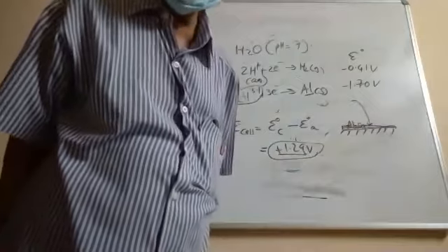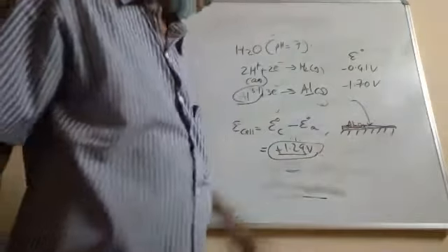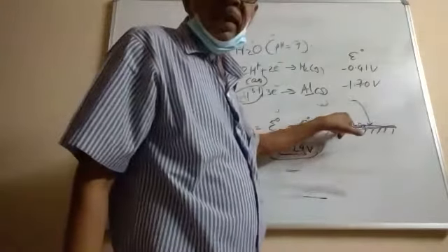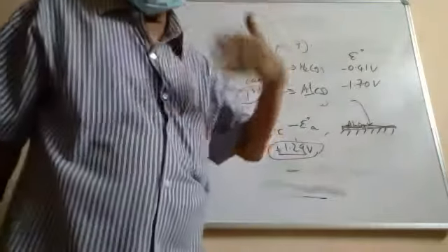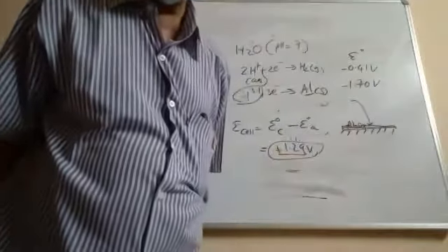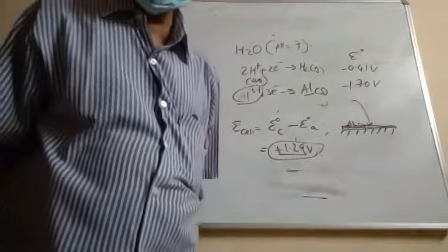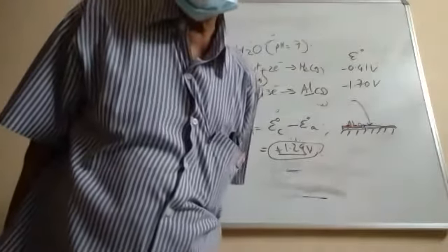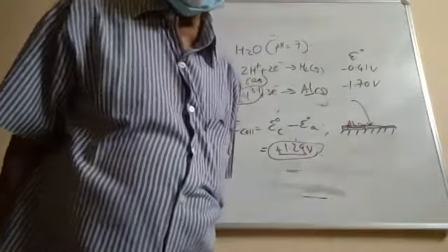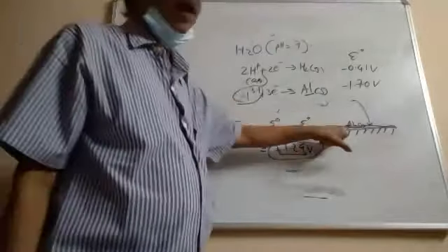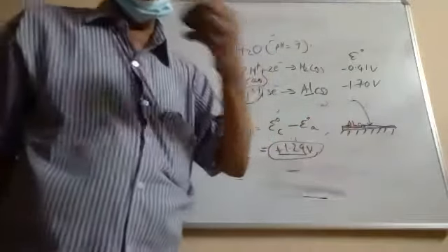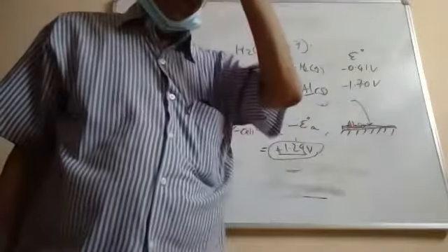It's not that the reaction is not happening, it's just that the products of the reaction now are detrimental to the progress of the process. It will not allow the next aluminum to react. So these things do happen, so you have to be very careful. So what does it tell you? If I don't have aluminum foil, but if I have a fine aluminum powder, that's going to react violently with water.